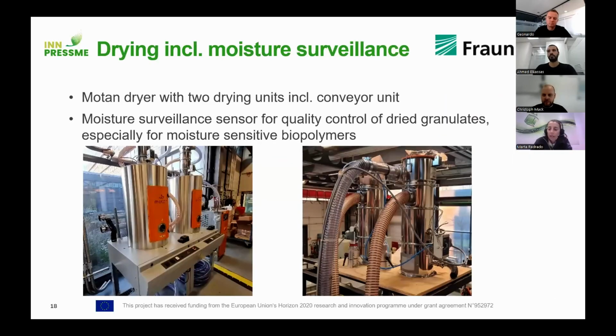Another upgrade done during the project was the installation of drying units with conveyors as well. And the main part of this is a moisture surveillance sensor to check and control the moisture of the polymers which have been dried before taking them into the compounding, because this is, especially for biopolymers, one of the critical values, because degradation takes place in the extrusion line if the material is too humid.